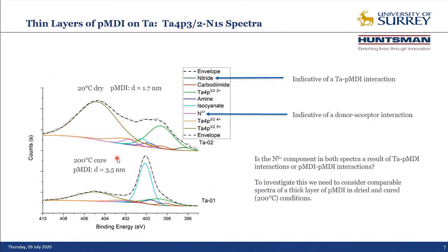There's also another component, which is this magenta line here. And this is nitrogen with a slight positive charge. And we think that's indicative of a donor-acceptor interaction. We can see it's here, only it's much, much weaker. But in the cured one, because of the thicker overlayer, we don't see any evidence of the nitride-like component. So the question arises, what is bringing about that slight delta positive charge on nitrogen?